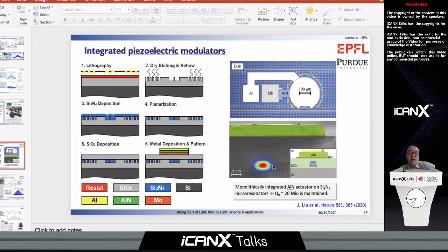I have a work about to be published where we monitored the Q factor over about 3-4 years, and we didn't see any Q degradation. But indeed, you have to regularly clean the wafer chip, but that's not for Q degradation. That's for the edge coupling, for the contact.